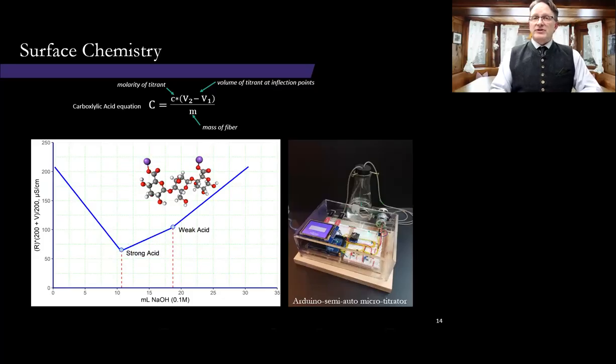I do want to make one point about surface chemistry and why I think it's probably the most important characteristic of nanofibers. The surface charge really determines the stability of the colloid formed in the solvent or solution that you've selected. If the nanofibers aren't designed for that solvent, it really doesn't matter what morphology you achieve, you'll lose all your capability or the contribution that NFC was designed for. Second, it also provides a backbone for further functionalization. So if you're going to take your NFC forward and make it hydrophobic or hydrophilic, or as a transport, this is the methodology that we use.